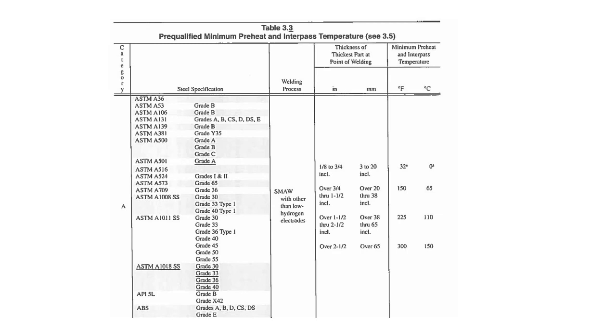In the left hand, it tells us our steel, ASTM A36, or way down here at the bottom, we've got API 5L, grade B or grade X42. So that tells us our material, and then we're going to weld it with stick, and then it tells us our thicknesses, and then over here on the far right, the minimum preheat and interpass temperature. So anything over 2.5 inches, we're going to need to preheat the material up to 300 degrees before we even strike an arc. That's what Table 3.3 is telling us.